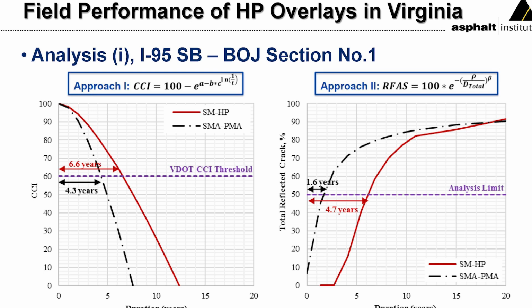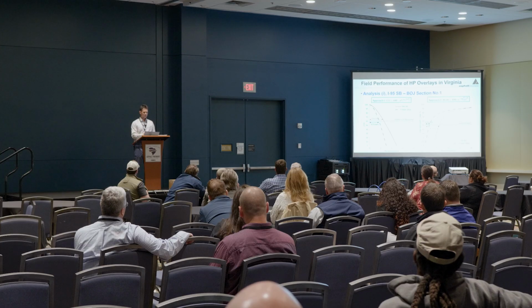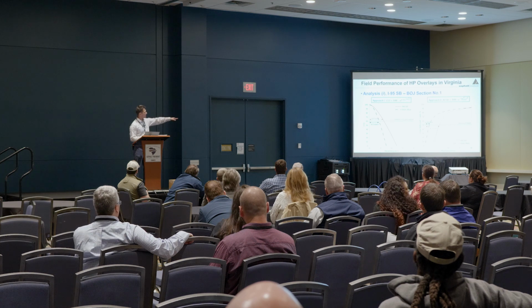And as a final step, they tried to convert this to a life-extending benefit. And what you're seeing here is anywhere from 50% to over 100% benefit, depending on the type of distress that you're measuring. With reflective cracking, it's a very substantial increase before they reach their critical point that initiates that rehabilitation.